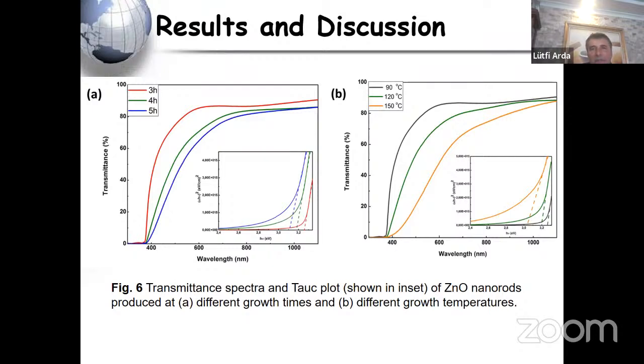After that, what is the reason for the change in transmittance of the nanorods? We can explain it like this. Many parameters affect the optical transmittance characteristics of one-dimensional zinc oxide nanostructures. The most crucial ones can be given as surface roughness, film thickness, crystal defects, oxygen vacancy, and impurities.